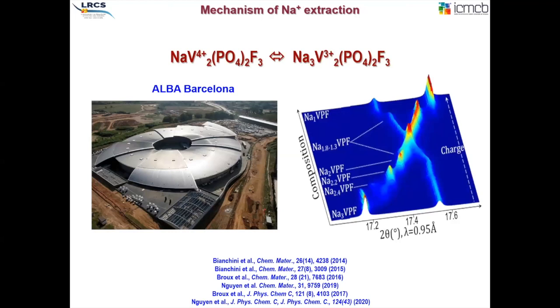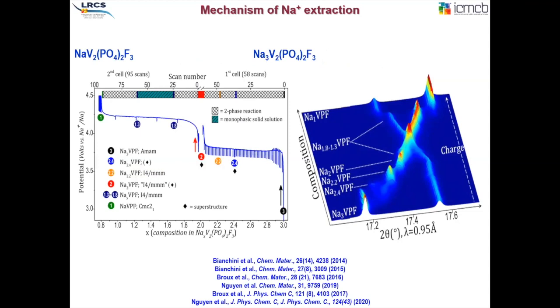Then we spent a lot of time, at least 6-7 years, doing structural studies, in particular at the ALBA synchrotron close to Barcelona in Spain, with our colleague François Fauth, to investigate the mechanism of sodium insertion and extraction. It happens that the mechanism looks simple from the voltage composition shapes with two separate features here. We were indeed able to identify many intermediate stages of sodium extraction with many intermediate phases characterized by different X-ray diffraction patterns. So this is rather fascinating.